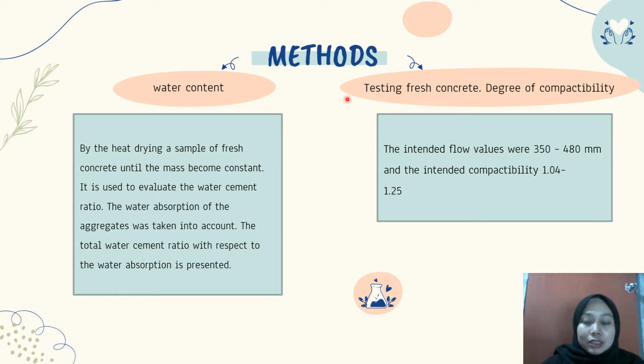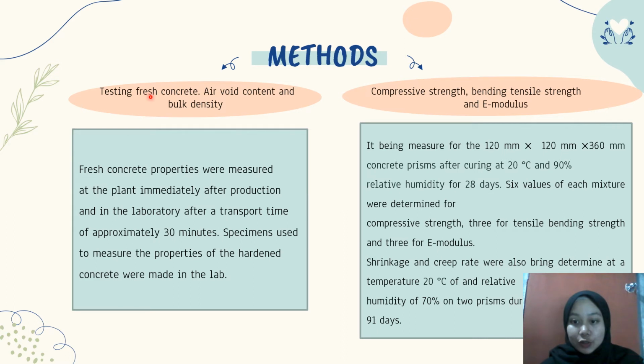And then the testing of fresh concrete, which is the degree of compactability. The intended flow values were 350 until 480 mm and the intended compactability is 1.04 until 1.25. Next, the method in this article is the testing of fresh concrete, which is about air content and bulk density. The fresh concrete properties were measured at the plant immediately after production and in the laboratory after a transport time of approximately 30 minutes.